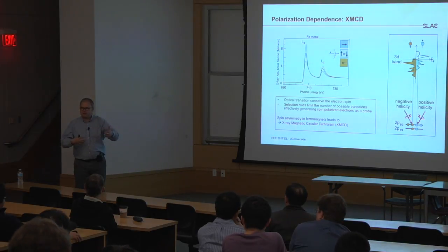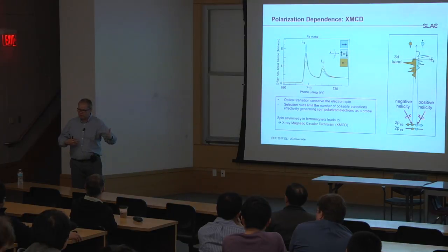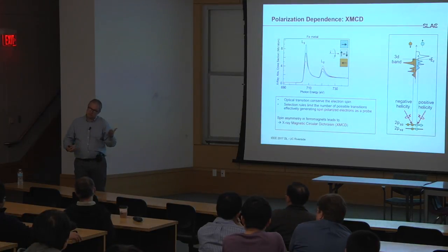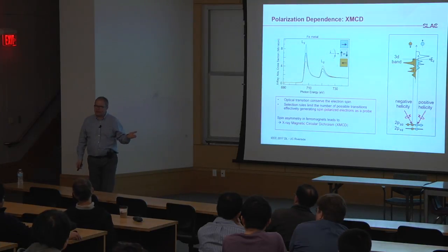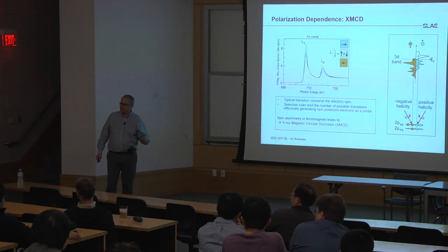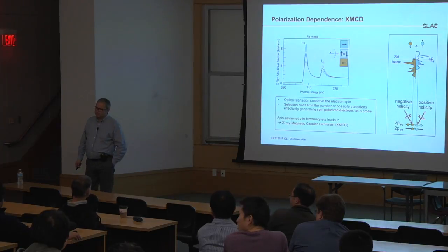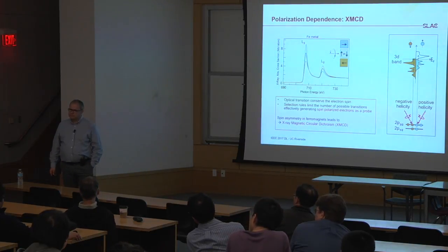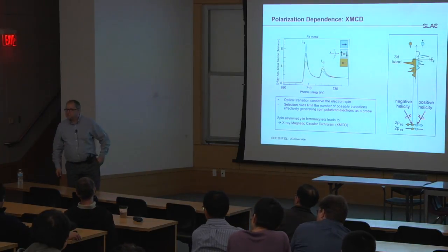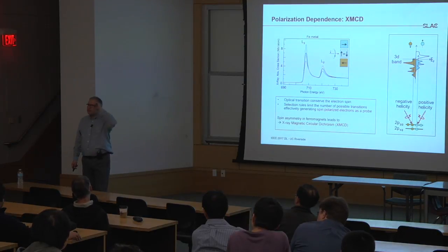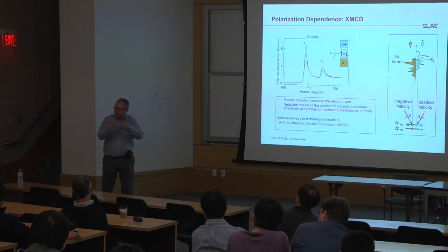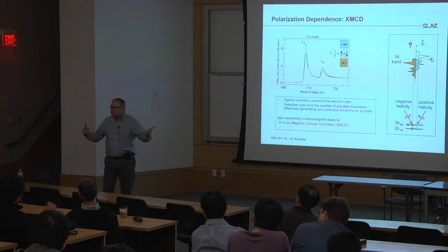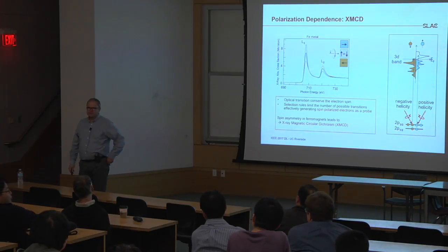Even if you go to 10 to the minus 9, you have like a minute per monolayer. So that is a problem if you want to detect a monolayer of graphene. And I think that's something that nobody really has addressed so far, how to deal with. You can do a monolayer of other elements. Just carbon is so difficult because when you irradiate with X-rays, you immediately get carbon on carbon, so it's kind of defeating the purpose.